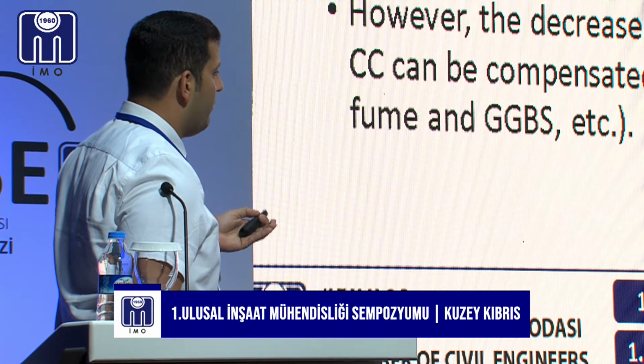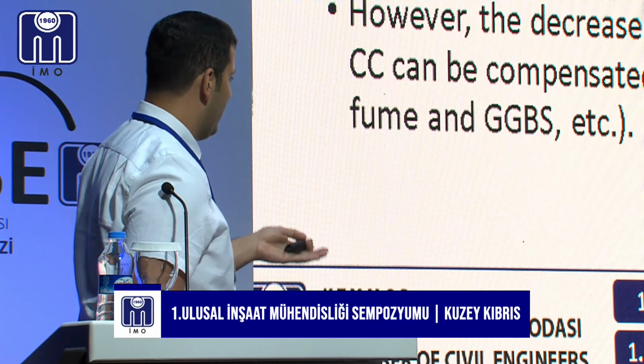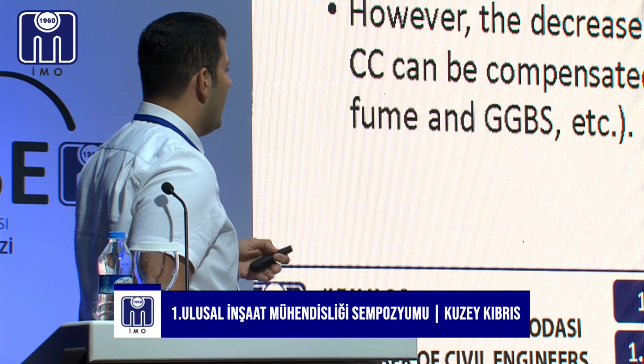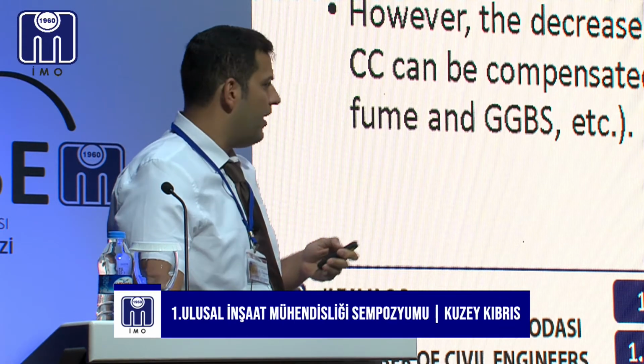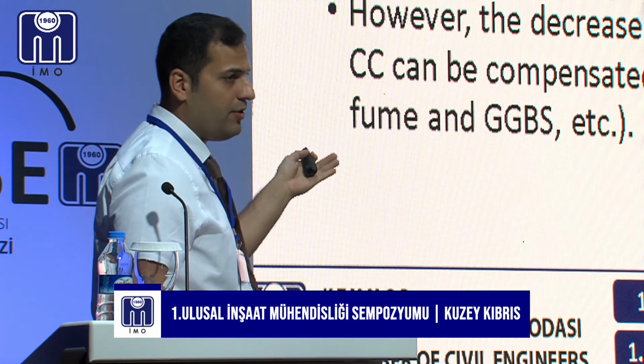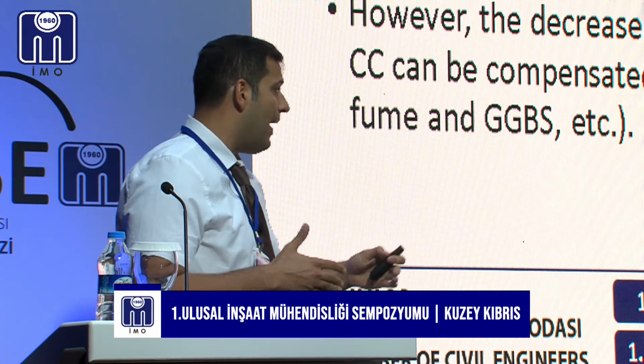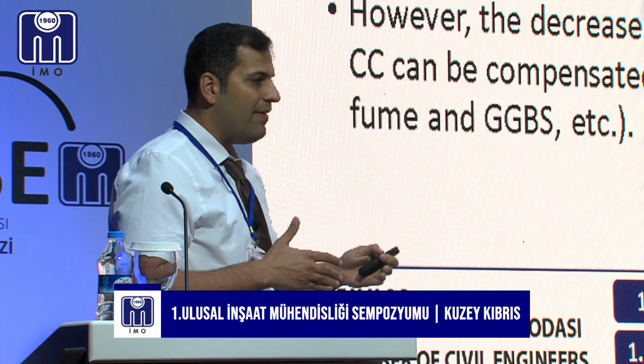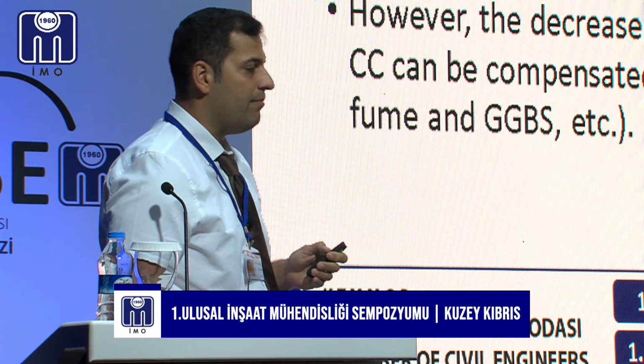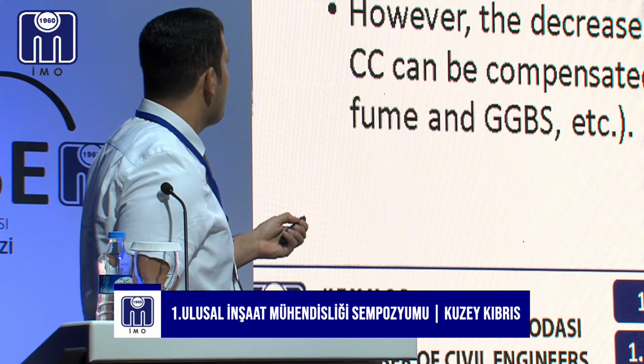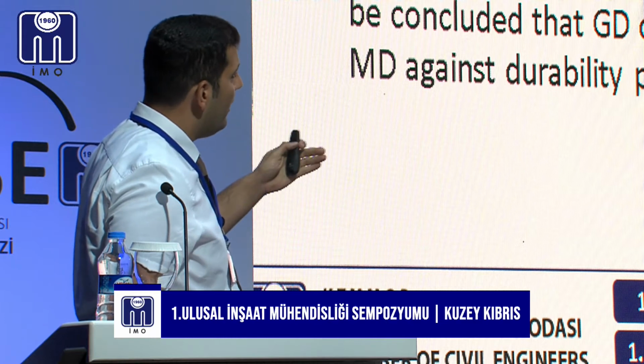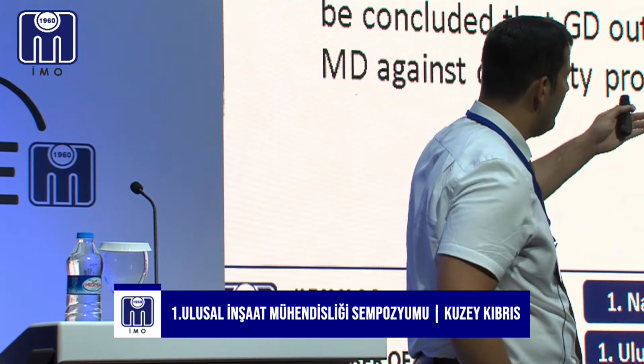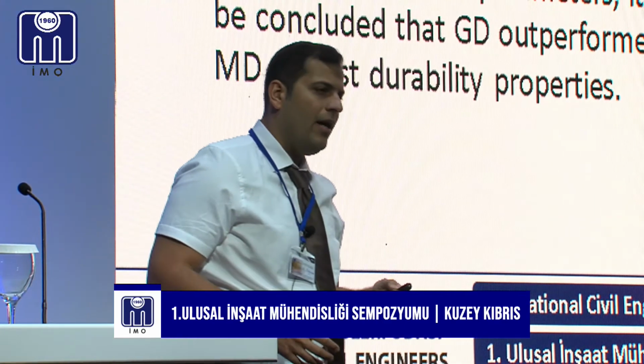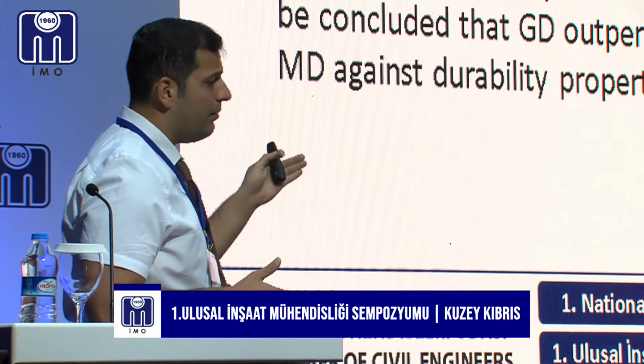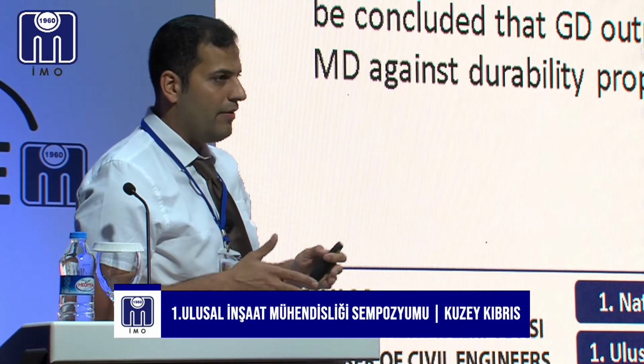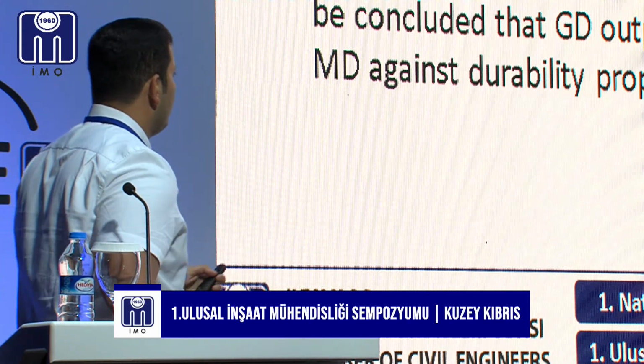However, the decrease in mechanical properties of marble dust and granite dust modified CC can be compensated by addition of other SCM like fly ash, silica fume, and GGBS. We had some articles showing that if we add fly ash and silica fume, it will mitigate this decrement of mechanical properties. For the durability, I just listed here the table, which shows that most of the articles believed that the durability of the concrete by adding the marble and granite dust will be improved. So there is no contradiction in this regard.